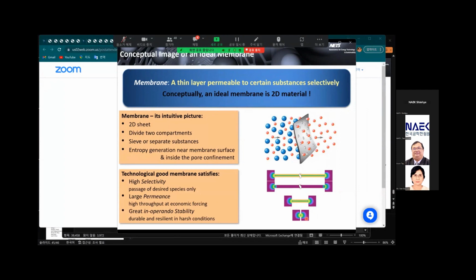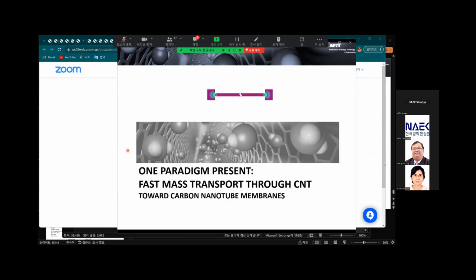By engineering the membrane in this way, we want to obtain a technologically good membrane that satisfies high selectivity, large permeance, and great in-operando stability. First, I will share with you a story of the existing paradigm on energy-efficient transport through carbon nanotubes, and then I will shift the paradigm by enabling an atomically thin membrane made with graphene. Here we go with the fast mass transport through carbon nanotubes based on a paradigm of minimizing the friction of transport.